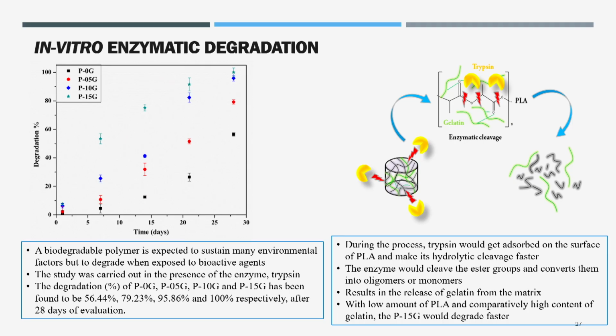And then we have to check, most importantly, that it's a biosystem. How do you know that a biosystem is a biosystem? You generate an ambience and you feed the material with an enzyme. A biosystem is expected to work without breaking during service time. But after service time, when you put it in soil, with that soil pH and humidity and the presence of enzyme, it should degrade. When it is operating, that enzyme is not there, so it is not degradable. But when you put it in the environment, pH is set, humidity is set, enzyme is also set, that will act and kill the material.